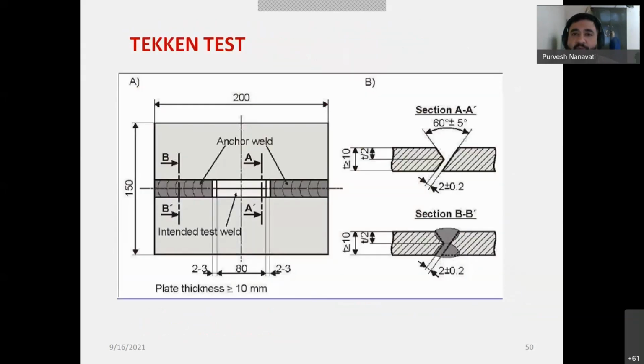Okay, so now this is a test setup for the Tekken test. You can see this is a typical test setup where the root is particularly slanted. It is a Y shape, so it's a Tekken shape, Y shape. You fill the material, and you have to first make the anchor weld. I'll show you. This is a typical test setup, and this is section AA. In section, this is how it looks, and this is section BB. You can see this is a weld, this is a finish weld, and this is a weld groove only.